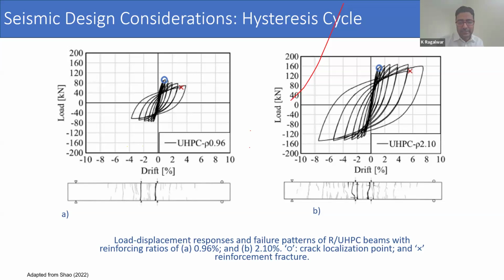Interestingly, a similar effect can also be achieved not by adding reinforcement, but by reducing fiber volume, not to zero, but maybe lower than 2%. By lowering the fiber content, the tensile strength of the matrix is slightly reduced. This reduction makes it easier to form multiple localized cracks instead of concentrating damage at one or two locations. As a result, steel plasticity gets distributed over more cracks, which increases drift capacity and delays the reinforcement fracture.